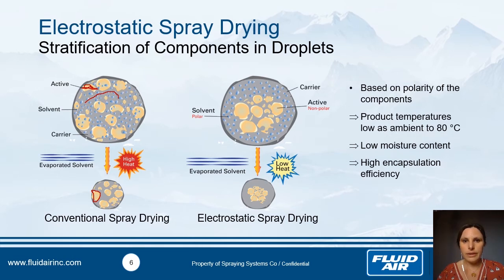In case of the electrostatic charge, we apply a charge and it helps to do a stratification of the compound in function of the polarity. So we use a polar solvent, and after we choose the carrier to have a polarity between the active and the solvent, and like that with the stratification of the compound we obtain really a perfect microencapsulation, because all the active compound is inside and you have something like a coating around your active, and you don't have oil at the surface, so you have a really great encapsulation.